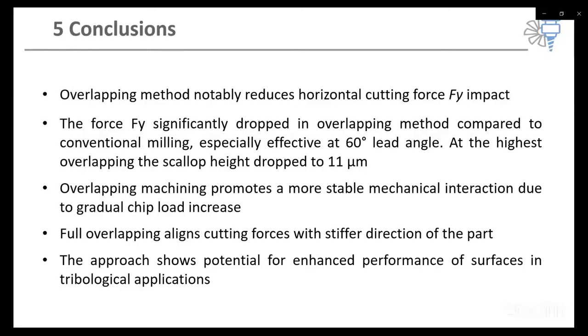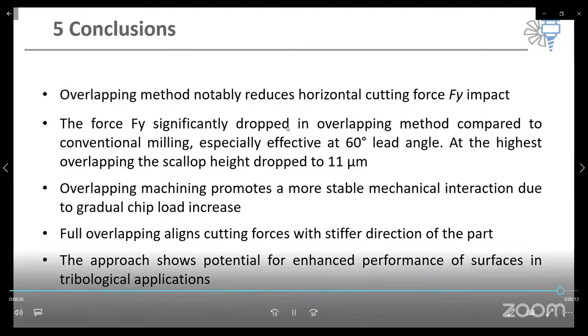The residual scallop height dropped to 11 microns, and the roughness also decreased, which potentially contributes to better tribological performance. Importantly, this was achieved without any additional fixture supports. Finally, the overlapping method promotes more stable mechanical interaction, aligning cutting forces with the stiffer direction of the part. These findings point toward a reliable strategy for improving machining accuracy and functional surface performance in thin-walled components.